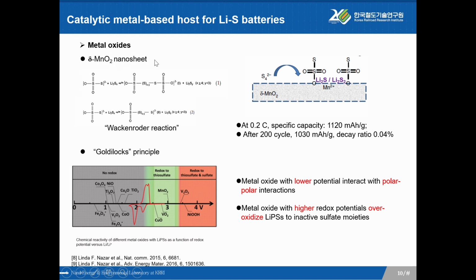This is metal oxide. MnO2 nanosheet is a very typical catalyst in lithium-sulfur battery. Under MnO2 catalysis, we can get a high specific capacity of 1,120, and after 200 cycles, it still can keep 1,030.